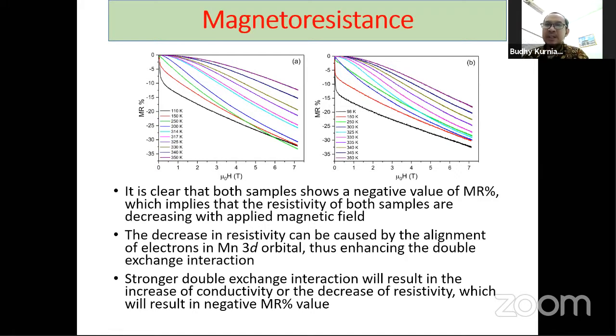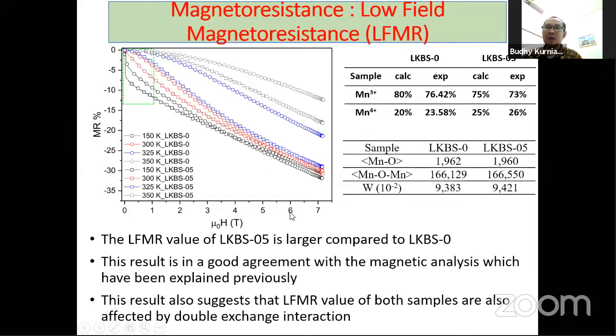What we found here, we show the low field magnetoresistance in our sample, and we found that the decrease in resistivity can be caused by the alignment of electrons in the manganese 3d orbital, thus enhancing the double exchange interaction. As we mentioned before, the contribution of manganese 3+ and manganese 4+ and oxygen will enhance the double exchange interaction. This is the low field magnetoresistance phenomenon that we can get from our sample.